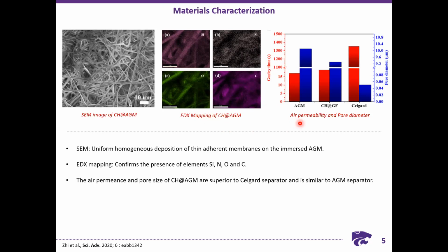They also calculated the pore diameter and air permeability to check how the coating affects the performance of the AGM separator. As you can see here, the Gurley time, which is the air permeability, that is how quickly a certain volume of air can pass through the separator or the interlayer, is quite similar to the AGM, and it is superior to the Celgard, which requires a longer time. Also, the pore diameter, as you can see from here, has decreased after coating, as is expected, in the case of CH at